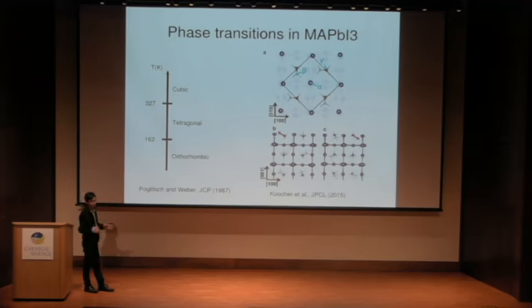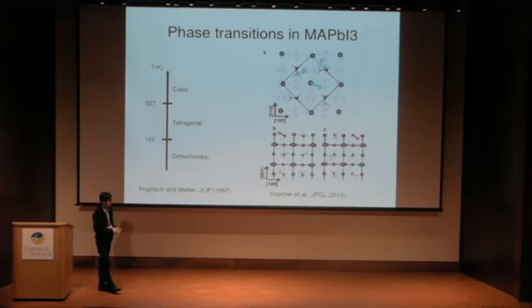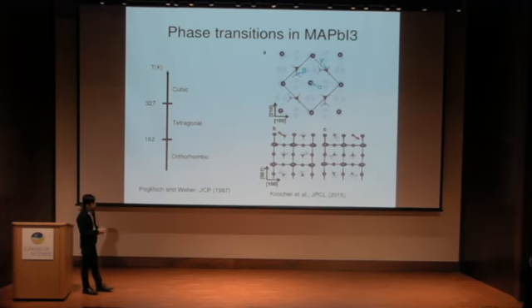You don't get very large-scale macroscopic domains. You get a lot of fluctuations in the orientations of the molecules. And I would say that the dynamics of this process is very important. Now, having said that, I would not rule out the importance of some kind of dynamic pseudo-ferroelectric order which contributes to the light power generation efficiencies of these materials. There are experiments which show that if you shine light on this stuff for a long time, the photocurrent goes up and up, and that may be attributed to increased order coming from exciting the molecules into more ordered states. So I would say that it's not completely clear yet.